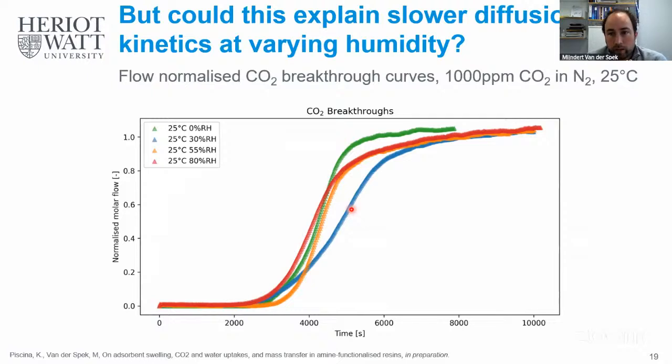And that was also confirmed in the gravimetric methods, where you can derive the diffusion coefficient or the LDF constant. We saw indeed that these were much lower at 30% relative humidity. We thought about this in many ways, and we tried to link this to the stoichiometry, but we couldn't come up with a reason why that would be the case. We just couldn't see why at 30% RH the kinetics of the adsorption would be slower than in dry conditions or at the other relative humidities.